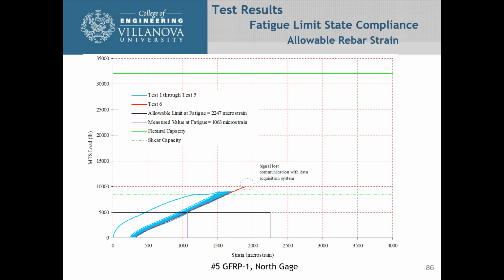So looking at a number 5 GFRP bar, the allowable rebar strain, we measured 1063, and the allowable is 2247. The one thing that we should note on this is once we started loading this thing up to failure, we lost the communication with the data acquisition. This may be that either the wire inside the sample came loose, or somehow the strain gauge became damaged.